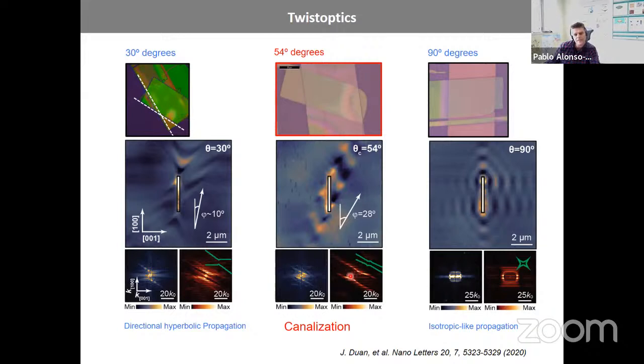This large case, they exist, but they have a very small wavelength, and then the propagation is small and the contribution is not very large. But here it is a large contribution. So what you will see is that if you increase this, if you open these flat bands, then you will have a smaller wavelength dominating the wave guiding. These fringes will be much smaller. They also will propagate much less probably. And if you make it closer together, it will be the other way around.